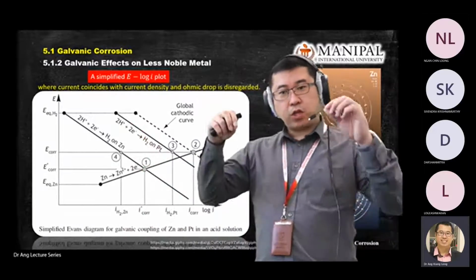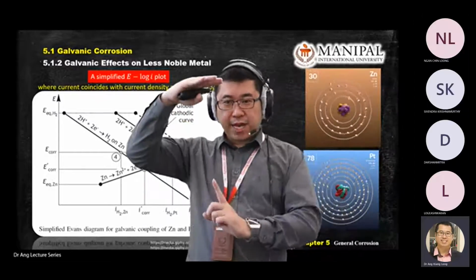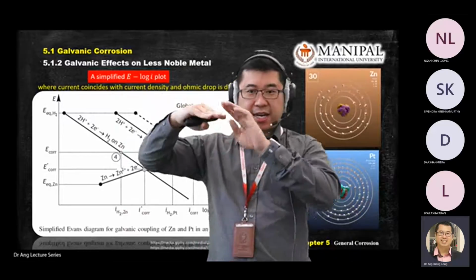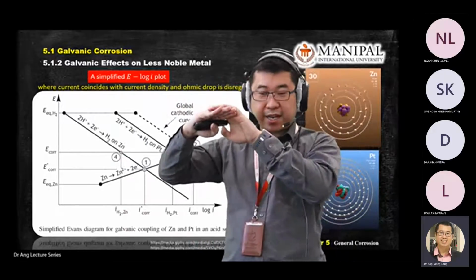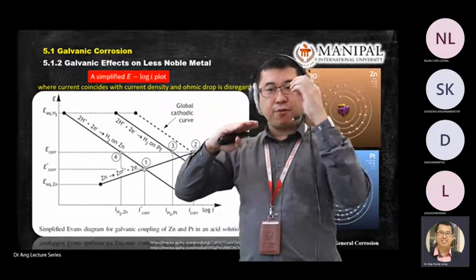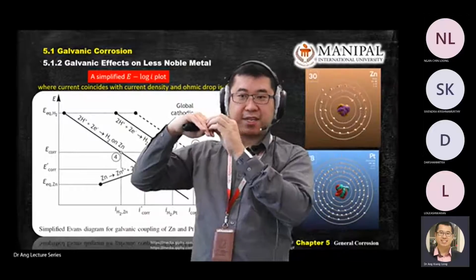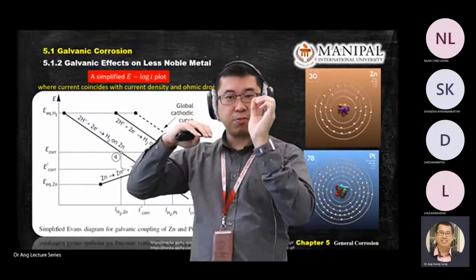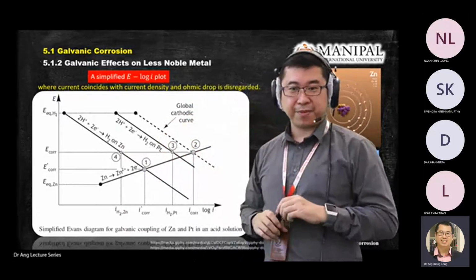That's why when you put platinum and zinc together, electrons transfer, and then H positive will combine with e negative to become hydrogen. Visually, you will see bubbles coming from the platinum side. Small bubbles. What are these small bubbles? From this equation, it is hydrogen gas.